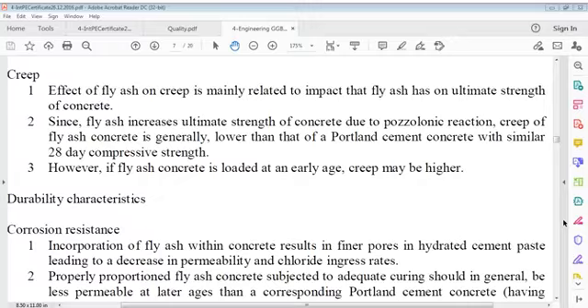Fly ash increases ultimate strength of concrete due to pozzolanic reaction. You know what is pozzolanic reaction. Creep of fly ash concrete is generally lower than that of Portland cement concrete with similar 28 days compressive strength. However, if fly ash concrete is loaded at an early age, creep may be higher.